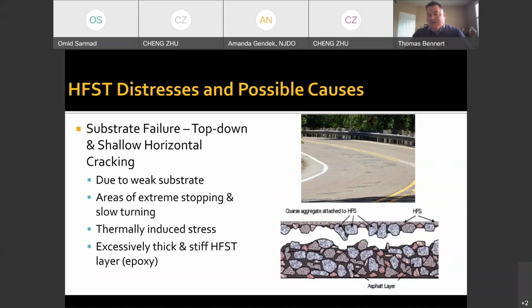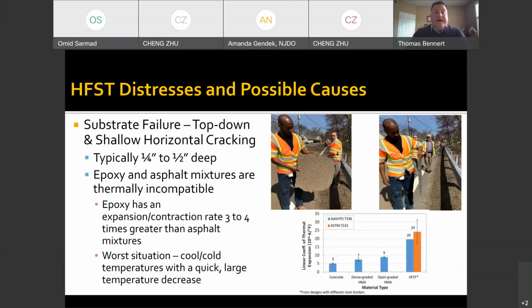And the epoxy thickness is very important on this material, because if it's too thin, the aggregates can actually ravel out, pull out, and you're left with just a sheet of epoxy. If it's too thick, the aggregates can actually be seated too deep, and then you're losing some of that friction. The other thing that happens is that if the epoxy is too thick, due to this thermal cycling, you can actually create a greater stress applied to the surface that can actually pull that HFST off. And that's generally what we were seeing in these sections.